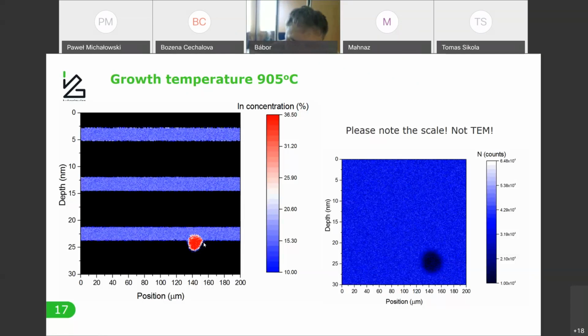And what's the beam diameter? Is the lateral resolution limited by the beam diameter or by something else? Yeah, I would say mostly by the size of the beam. So you have the beam of 6 kiloelectron volts, and the beam width is like 1 micrometer, something like that. Yes, it can be done, but it's also very difficult to optimize, especially at the beginning.